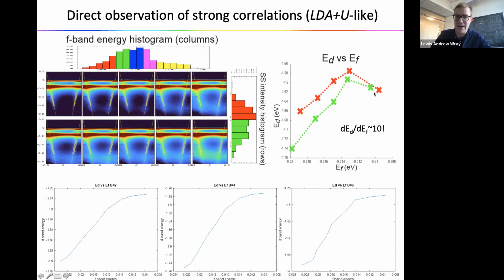So as you try to pull the F band down in energy, you're squeezing some electrons into the F band, but you're squeezing a lot more into the D bands, because the F band is effectively resisting taking on more electrons. And what that looks like in our data is that the D bands pull further beneath the Fermi level. In fact, we took a tight binding model from the literature and threw in a Hubbard U term. You set it to 2 eV on site, you get something that sort of matches the data.